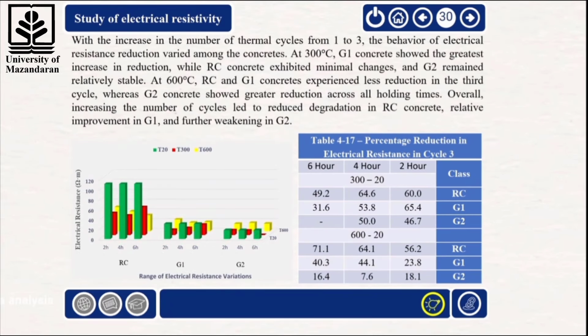In examining the effect of the number of thermal cycles, it was found that increasing the cycles from 1 to 3 produced different behaviors among the concretes. At 300 degrees Celsius, G1 showed the highest increase in resistivity reduction, whereas RC exhibited minimal changes and G2 remained relatively stable. At 600 degrees Celsius, RC and G1 experienced lower reductions in the third cycle compared to the first, while G2 displayed greater reductions across all holding times.